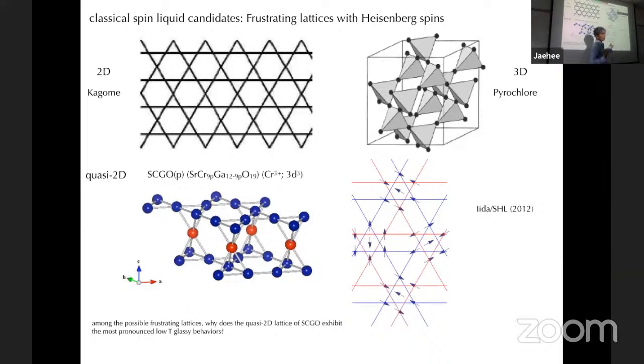this system also can have a zero energy mode at the mean field level, but it is not local. Its extent is partial, so only a partial number of spins are involved. Let's say we rotate these 3, then the remaining spins don't care. Then if you go next, you have to rotate this together, this together, and so on. As long as we want to stay in the classical ground state manifold, we have to rotate all the spins along here and go here, along here. So it's a straight line, almost straight line in this particular case. And if we have slightly different configurations, then we have to rotate along curved lines as well. I call it spaghetti mode, straight spaghetti or curved spaghetti mode.